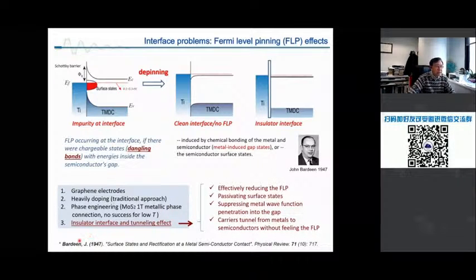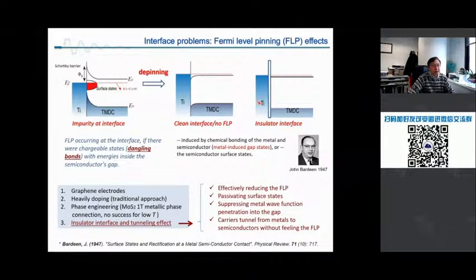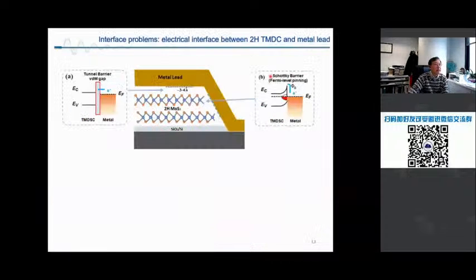People also thought about a way to use an insulator between the semiconductor and metal leads, so that these two materials cannot see each other, and there's no Fermi level pinning effect. And that's true. This can effectively reduce the pinning effect. But the drawback is that electron injection through the channels has to go through the tunneling effect. Tunneling. Yeah. And that limits the carrier injection efficiency. So it's still not a good solution.